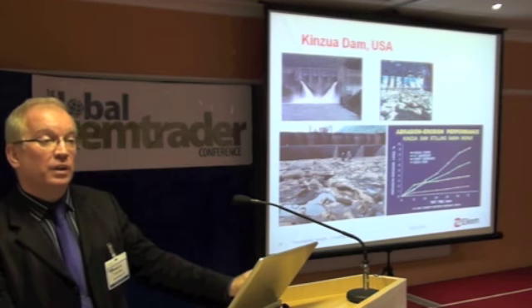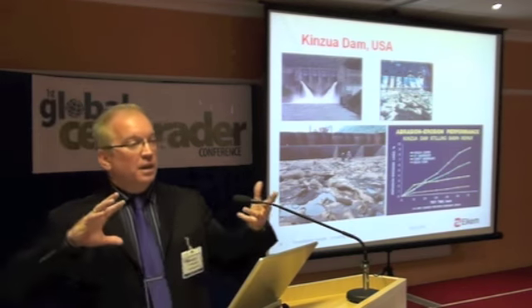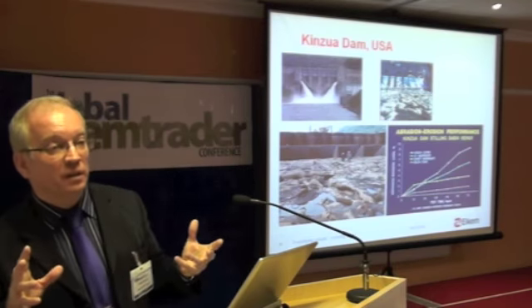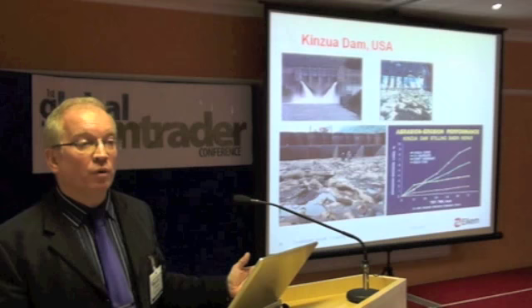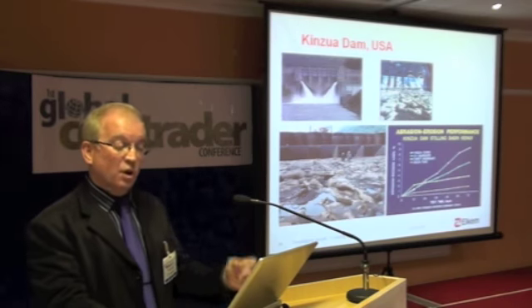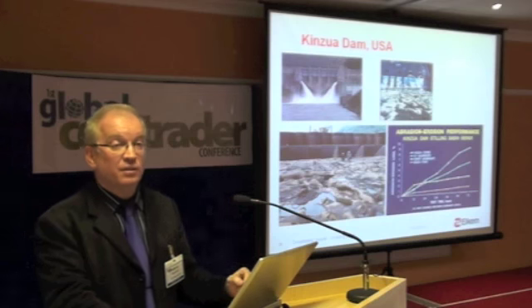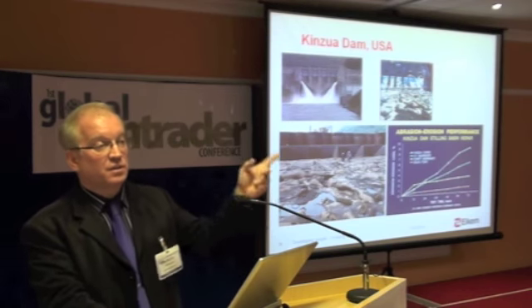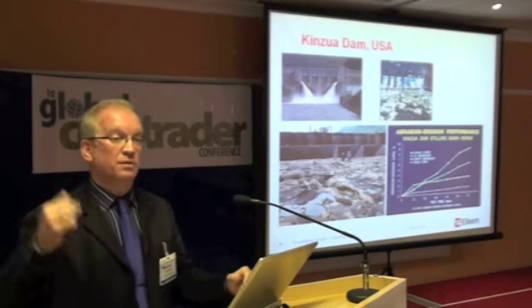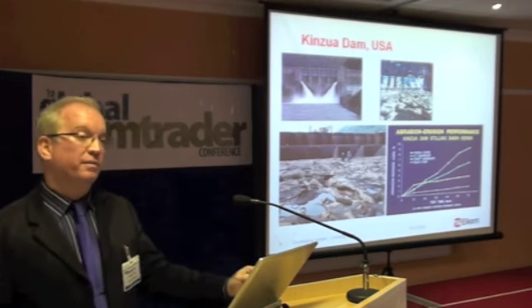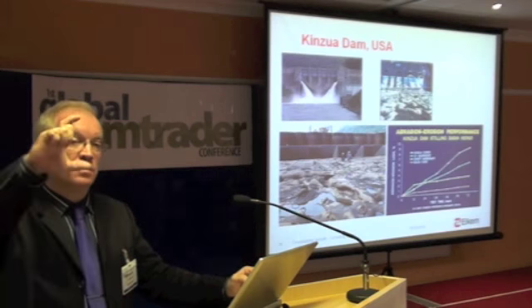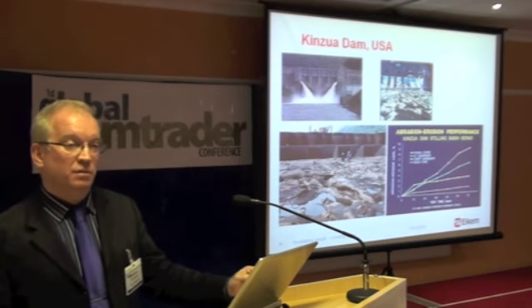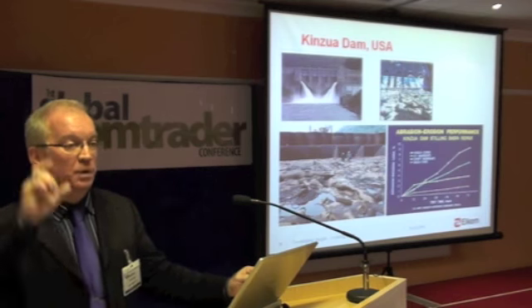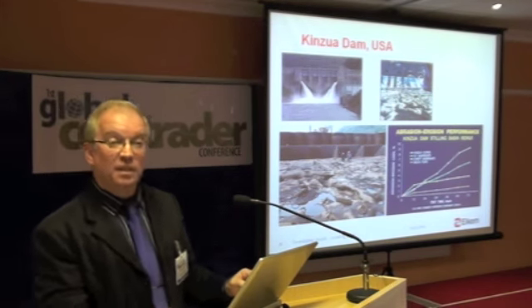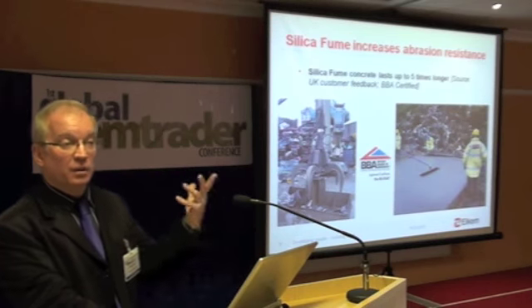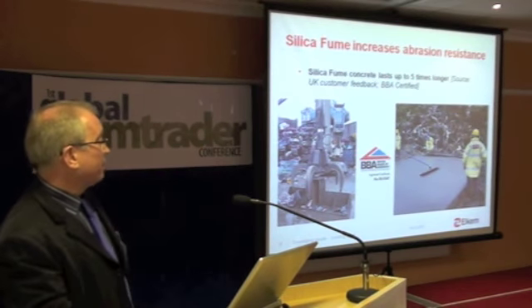They replaced it with a local aggregate wrapped in a matrix that was Portland cement and silica fume. The bond meant that there was less abrasion, so it's been down there ever since. 67 to 74, 74 to 83, it's been down since 83. In 2008, 25 years on, they found about 3 inches. 3 inches, not 3 foot, but about 3 inches in a few places. That's the sort of durability we've got to be looking at with our projects. We have a few more.